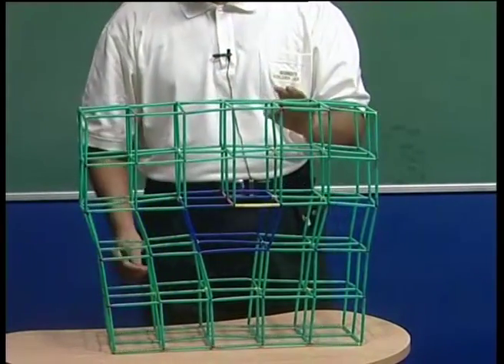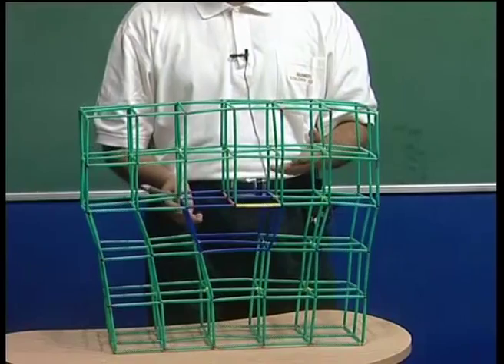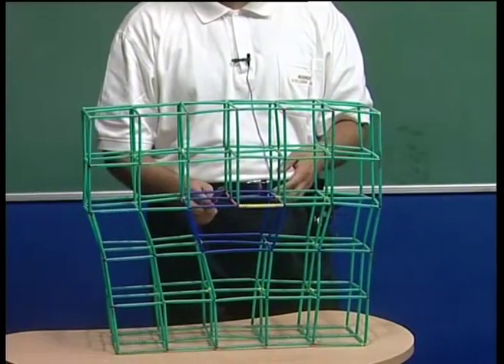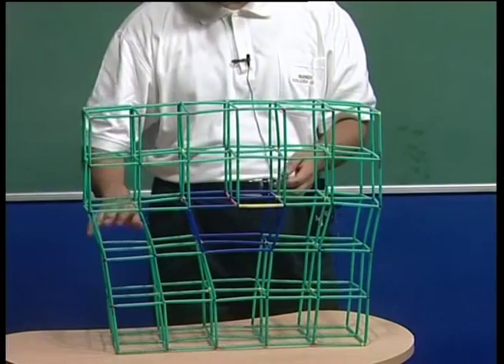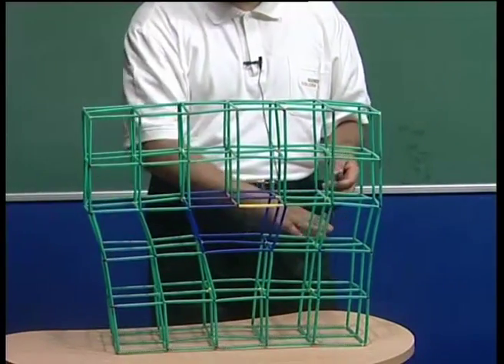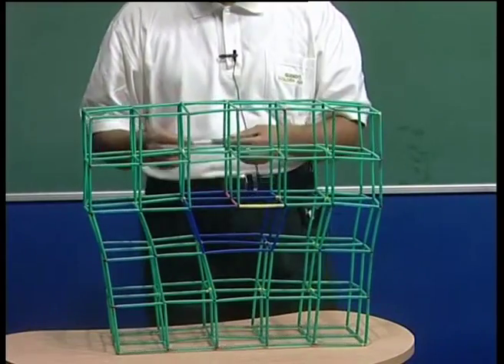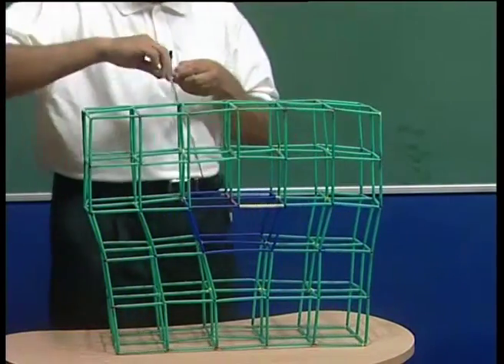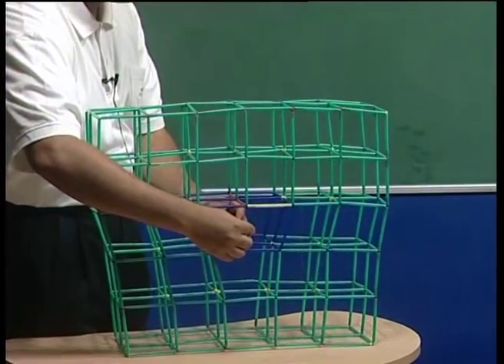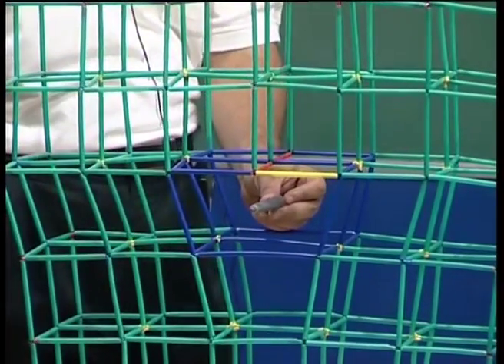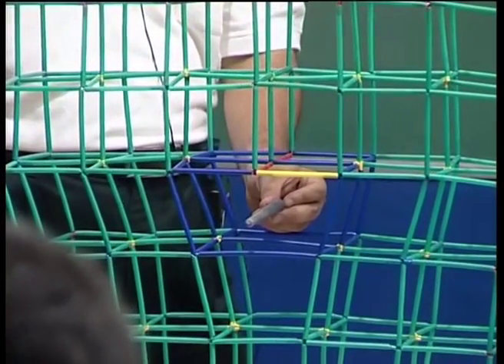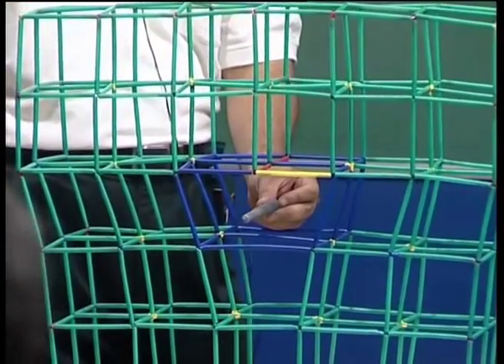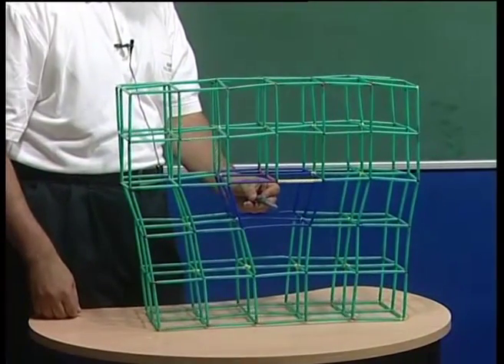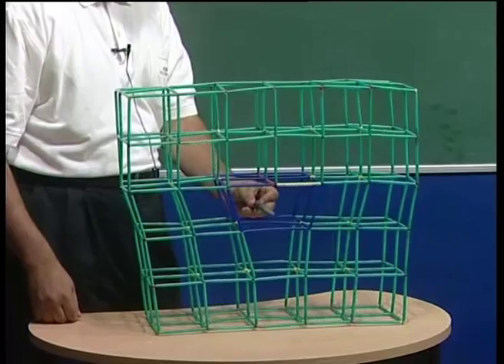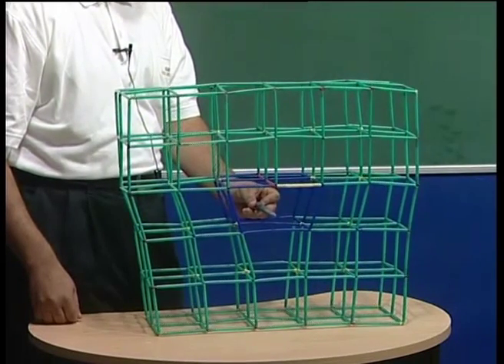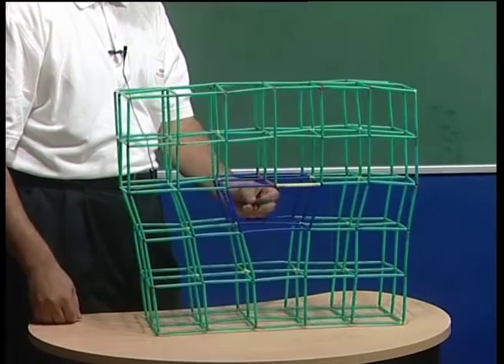Now an important thing, of course, it is very easy to understand an edge dislocation because it is associated with an extra half plane of atoms. Now this plane on which this dislocation line lies is called a slip plane. Now the T vector is nothing but a line vector which goes into the plane, because now my dislocation is going inward, and now my T vector is this pen, as you can see, which is the vector which describes the line of the dislocation. Because this is now a straight dislocation in this crystal, my T vector is not changing from position to position. But if it were a curved dislocation line, then not only would the T vector change, but also the character of the dislocation would change, as we shall shortly see.